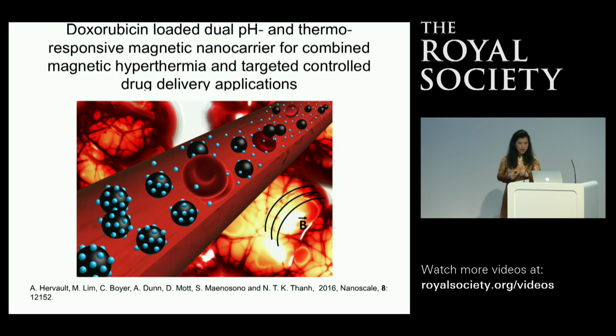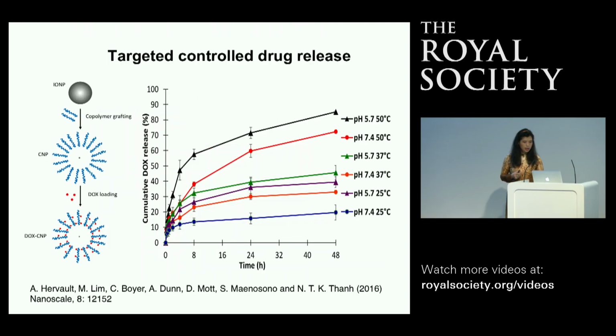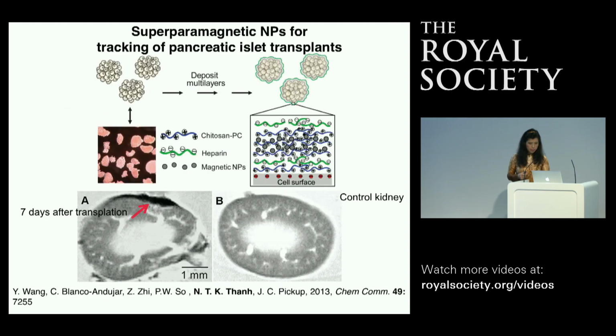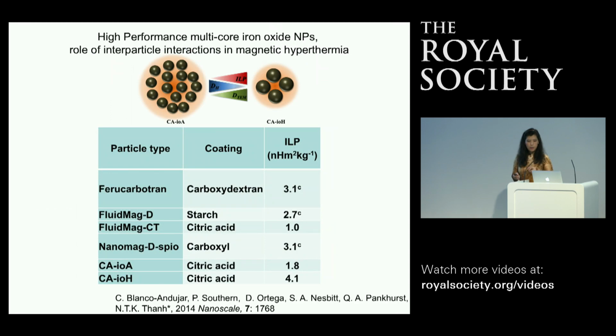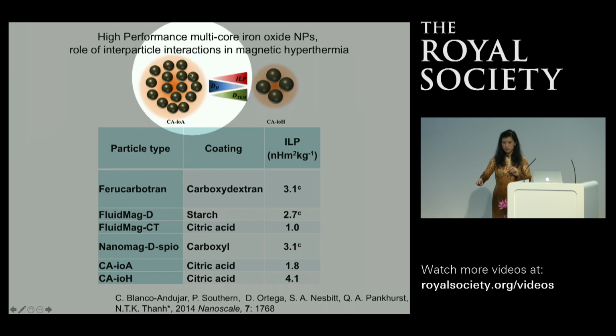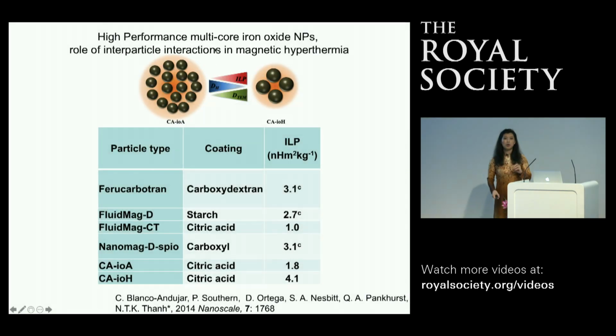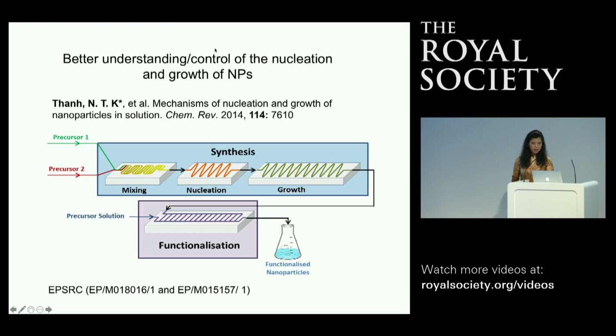And one other application is magnetic hyperthermia, where we use an alternating magnetic field, and then you can heat up the nanoparticle inside the body and release the drug, and we can also look at the release profile of the particle. And here, the different magnetic nanoparticles have different properties, because you can see that they have a different heating property when they aggregate.